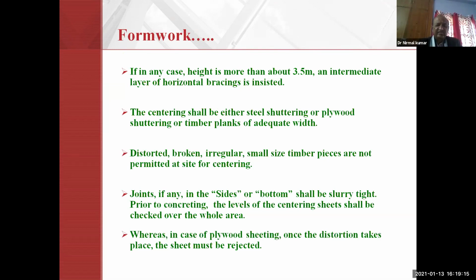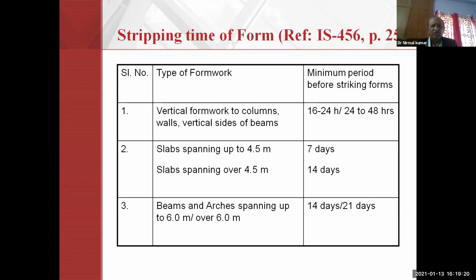This is about formwork and the stripping time of formwork from the quality point of view. Vertical formwork to columns, walls, vertical sides of beams should be stripped within 16 to 24 hours or 48 hours. Slab spanning up to 4.5 meter should be stripped within 7 days. Slab spanning over 4.5 meter should be stripped within 14 days. Beams and arches spanning up to 6 meter or more than 6 meter, the time limit is 14 to 21 days.